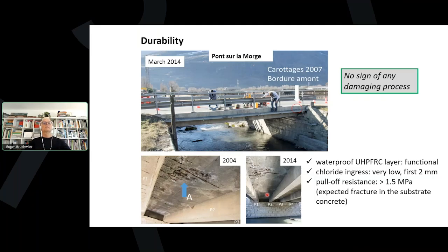Now let's look at the durability. This very first application from 2004 is actually a case where we look at the long-term behavior. And we have now more than 20 years of observations. And when you look here at this photo from 2004, the underside of this short bridge showed actually rebar corrosion. And intentionally, we did not repair this underside. We wanted to observe whether there is ongoing deterioration of this underside in reinforced concrete.